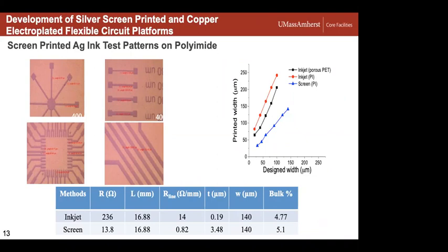And if we compare resistance and line resistance here, we're seeing that we're getting definitely factors anywhere from beyond 10 and so on. And that's because the inkjet also is very limited in thickness. A lot of times you're only getting about a couple tenths of a micron in thickness, and a micron is really where it tops out.